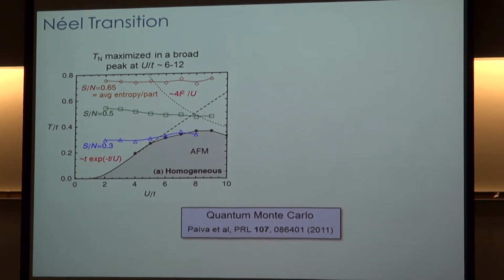So this is in a little bit more depth what that phase diagram looks like, the transition into the Néel phase. This is assuming a homogeneous density. This line marks out, as a function of U over T, the boundary between antiferromagnetism and a non-magnetically ordered phase. And you can see you need to get entropies that are below about 0.3, so about a half of log 2 in a homogeneous system, in order to get into this antiferromagnetic phase.